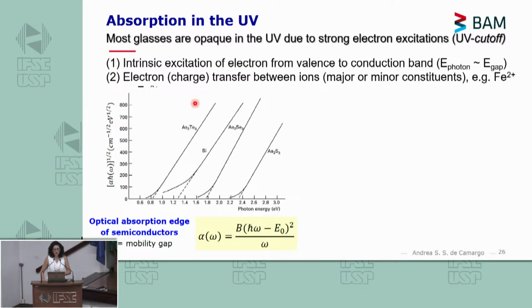More precisely, instead of using E_G, which we often call gap energy for semiconductors, it is better to use this E_0 here, which is the mobility gap between the mobility edges of the valence and the conduction band, okay? So that's why I wrote this particular equation that characterizes the absorption coefficient as a function of frequency for different mobility gaps, E_0, okay? If we look at this graph, it plots the absorption coefficient as a function of photon energy, and we have different semiconductors here. You can see that E_0, of course, will change. By this equation, you can see that it can be obtained by extrapolation of the linear parts of these curves.